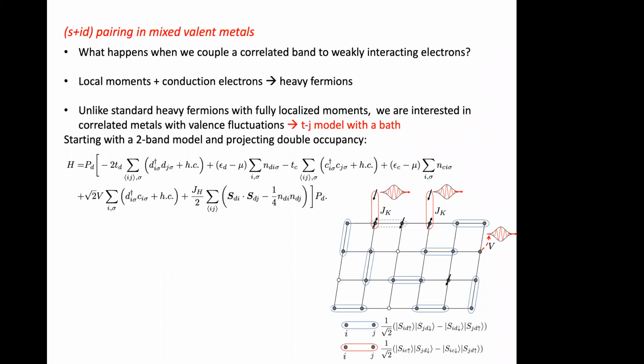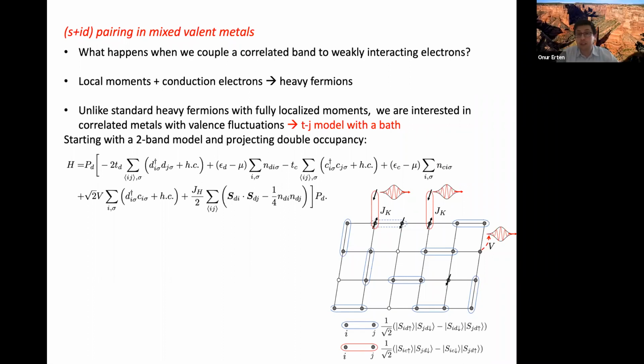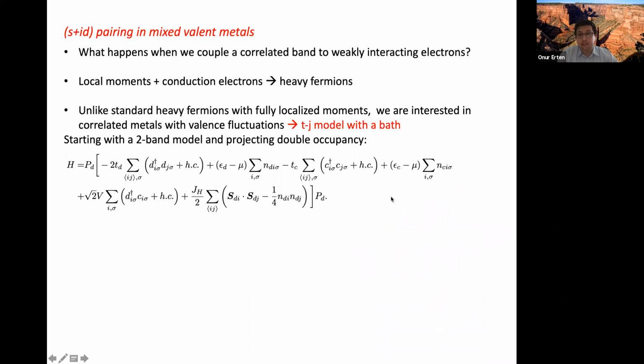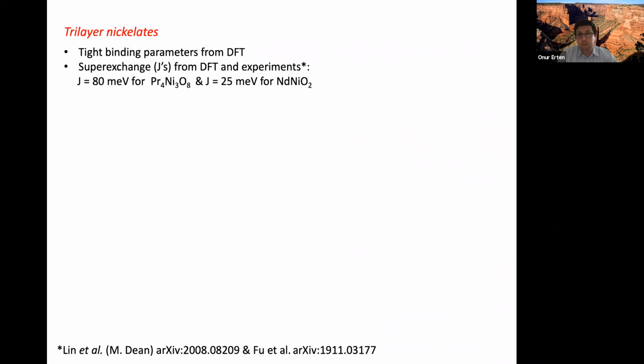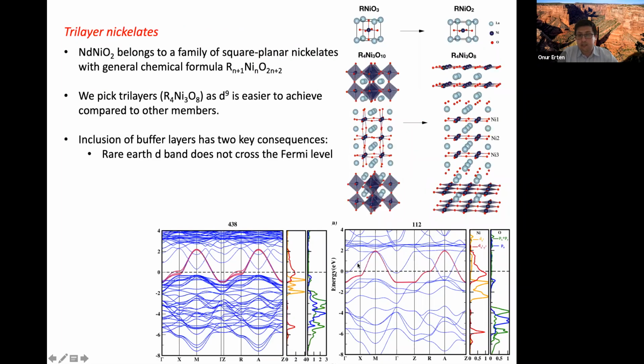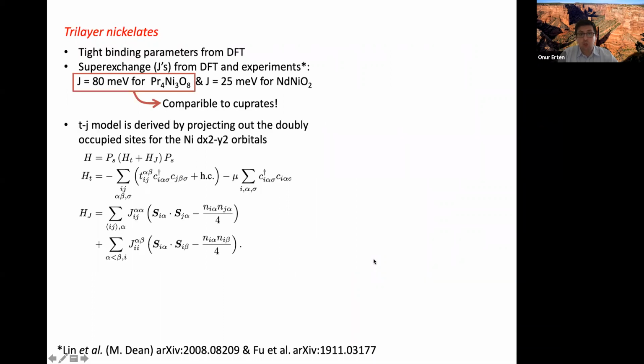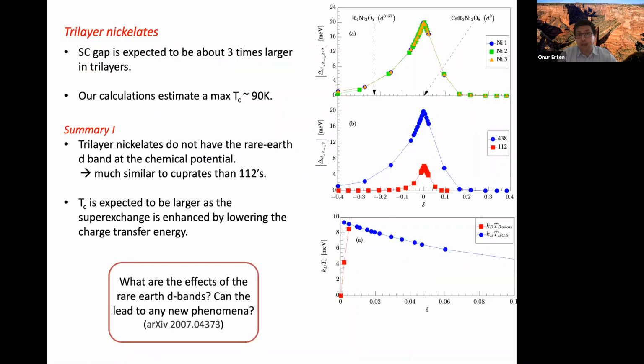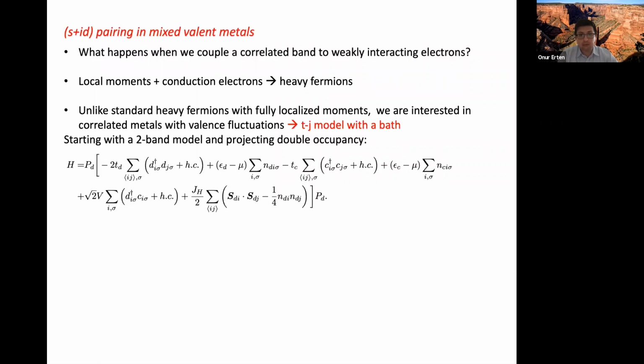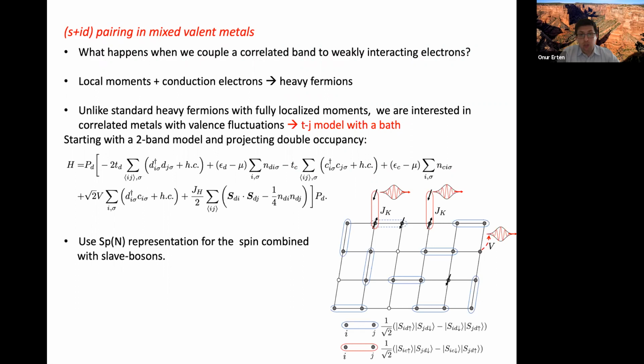This bath is not bosonic, right? It is a fermionic bath. It is to mimic the bath that comes in these systems where there's some extra band that is in some sense coupling with the strongly interacting band. So it mimics this extra band, the rare earth band in nickelates. And once again, for the spin, we are doing a symplectic large-N representation and combining it with slave bosons. And we decouple it in every channel and solve everything self-consistently.